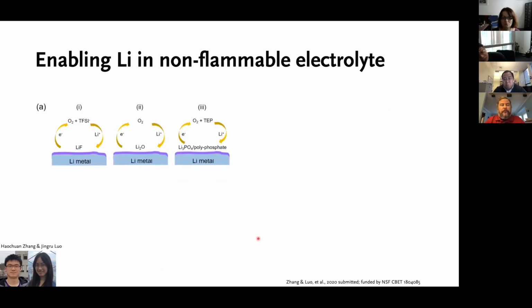So Hao Chuan and Jin Ru proposed a number of hypotheses on this process. The first one they tried to test was that the electrochemical characterization proves that oxygen could first be reduced on the surface of lithium. Once reduced, a one-electron process will give you a superoxide radical. And this radical could decompose the salt. They paid attention to this because in the literature there is a trend where people use highly concentrated salt, particularly TFSI-based salt, because the decomposition product contains fluorine, represented here as lithium fluoride, which can serve as a functional SEI layer.